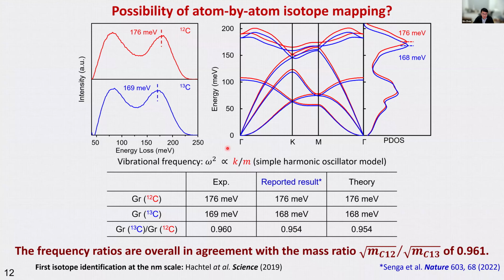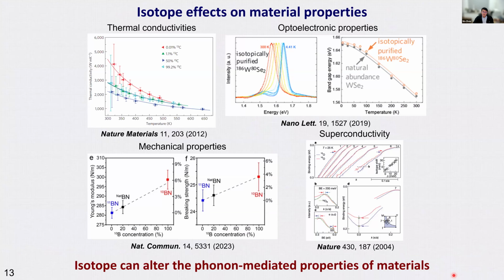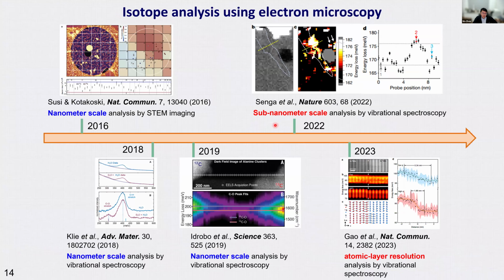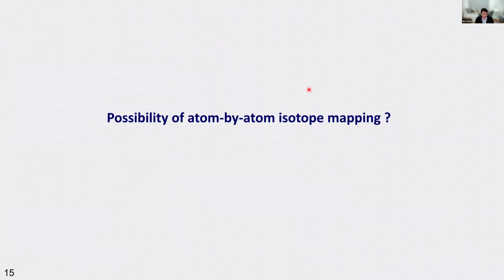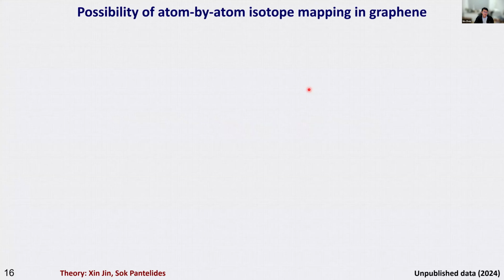So this is done at the macroscopic scale, or in Senga's paper, it's done at the sub-nanometer scale in the electron microscope, so that's already the best, almost a direct world record. At that sub-nanometer scale, they can map out the distribution of carbon-13 and carbon-12 in the carbon-13 matrix. So the question we raised is, is it actually possible to identify the isotopes atom by atom? That would be the ultimate goal for structural analysis. So let's first see whether it's possible.